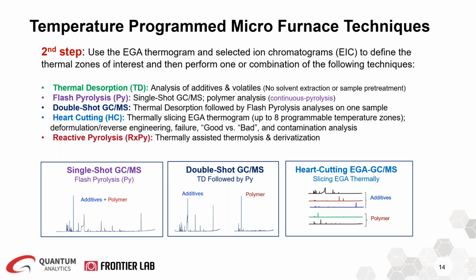You could also perform flash pyrolysis, which is also called single-shot GCMS, and is the fundamental technique for polymer analysis. In this mode, the furnace is typically programmed at high temperature to break down the polymeric and heavier compounds into smaller fragments. The key here is that you are performing a continuous pyrolysis, where the sample is not subjected to heat prior to the pyrolysis,